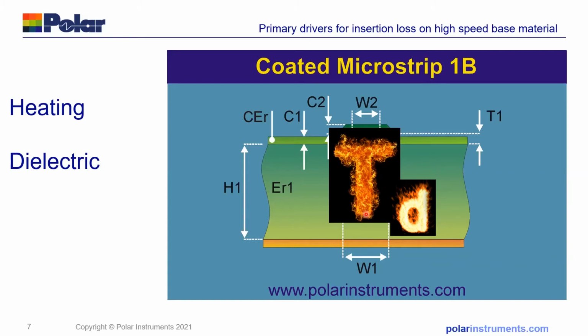The higher the tan delta, the more heat that gets lost. So obviously something like NF30 is going to have very, very tiny losses. Something like FR4 will have significant power losses through heating. So heating of the dielectric is one area you have to be concerned of.